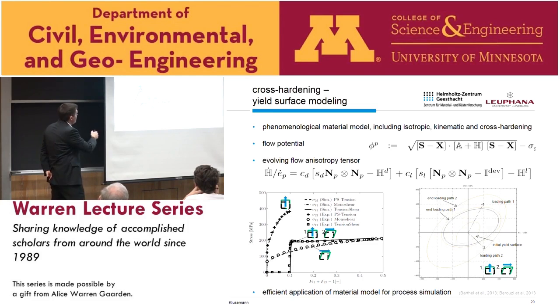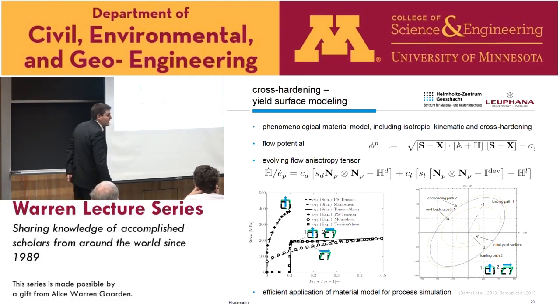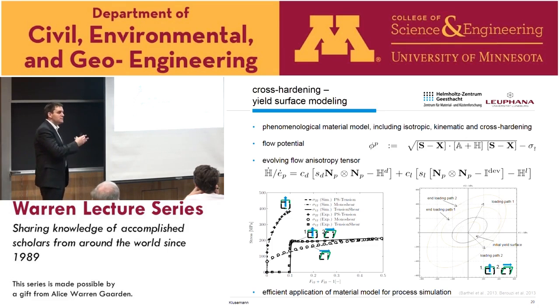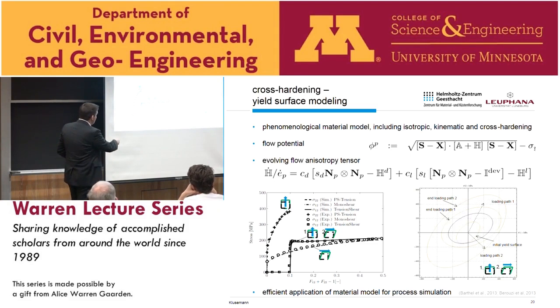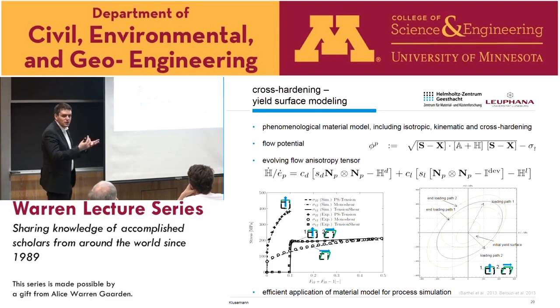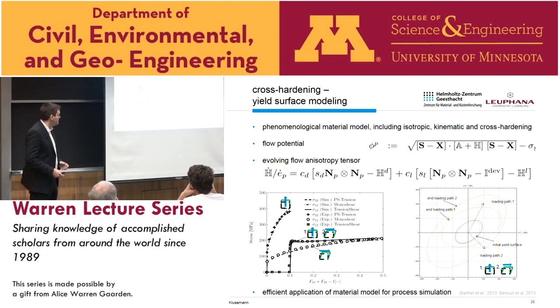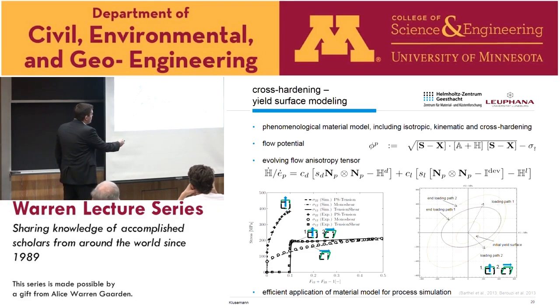Our evolving flow anisotropy tensor has two contributions. One contribution comes from the dynamic part, and one from the latent part. And of course, as we saw already in the experiment, the dynamic part we assumed to be 0 because we accounted for that already by the isotropic hardening contribution. So we only had to identify our latent hardening contributions. And for this, we of course used several tests. We used the classical plane strain tension test, we used shear tests, as well as plane strain tension followed by a shear test, as well as uniaxial tension to identify our material properties. And we could capture this kind of behavior very accurately, as just identified.